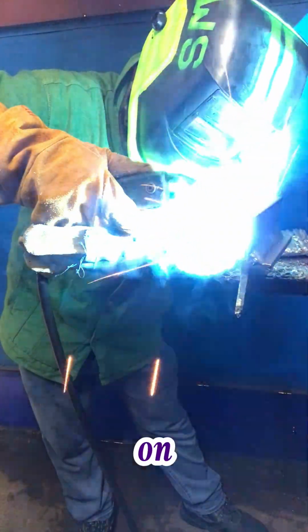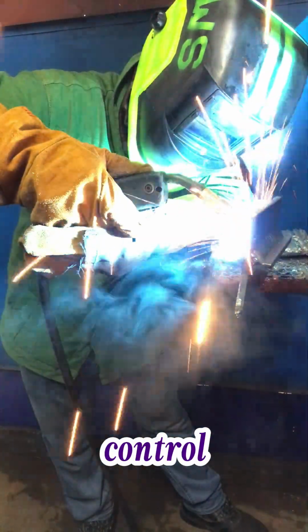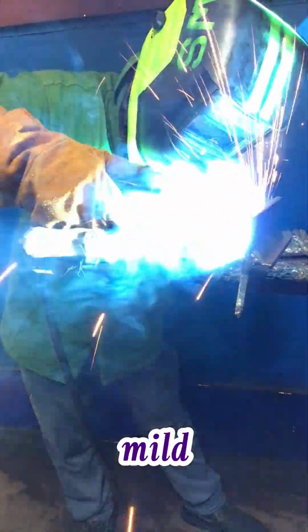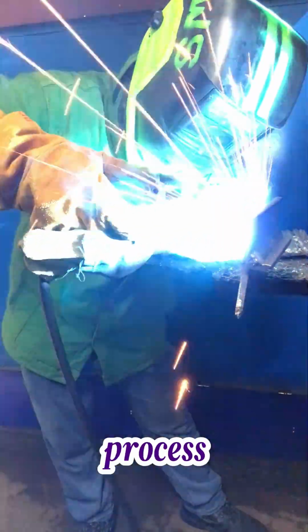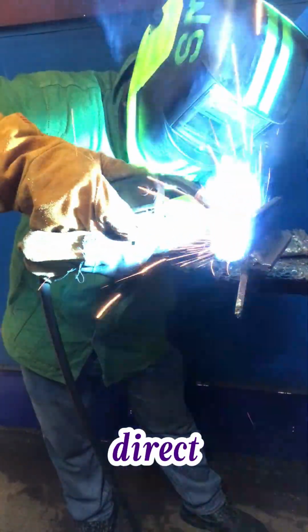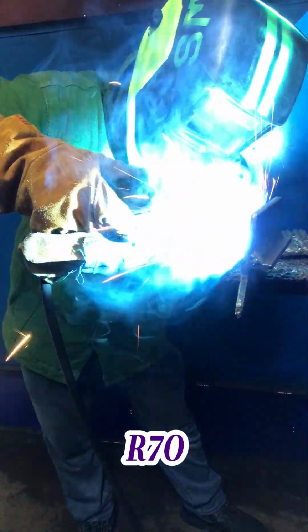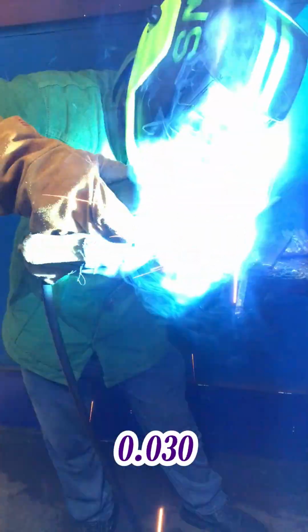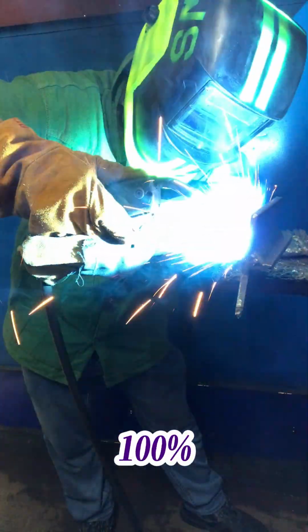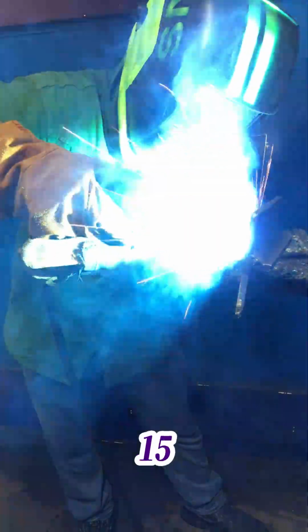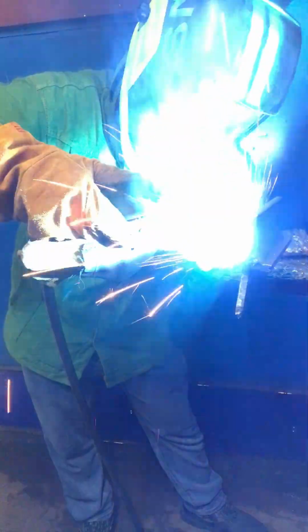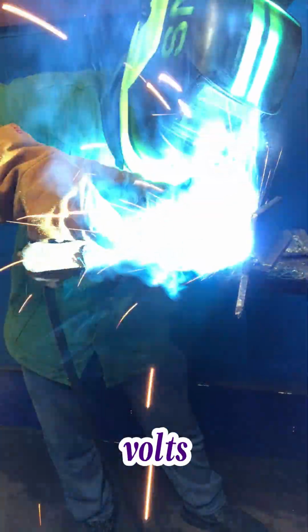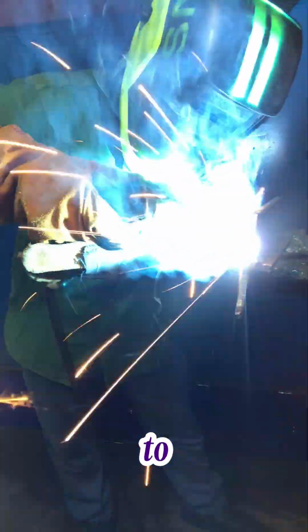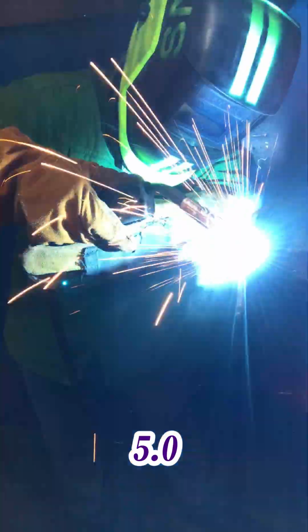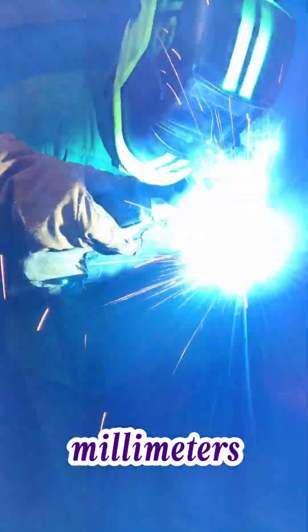Getting your machine settings right on Day 3 makes or breaks your weld pool control. For short-circuit GMAW on 6mm mild steel plates, set your machine to these baseline parameters: process and polarity GMAW, DCEP, direct current electrode positive. Filler wire ER70S-6, 0.8mm, 0.030. Shielding gas 100% CO2. Gas flow rate 12 to 15 liters per minute, about 25 to 30 CFH. Voltage 18.5 volts to 19.5 volts. Wire feed speed, WFS, 200 to 220 IPM, approximately 5.0 to 5.5 meters per minute. Wire extension stick out 3/8 to 1/2 inch, 10 to 12 millimeters.